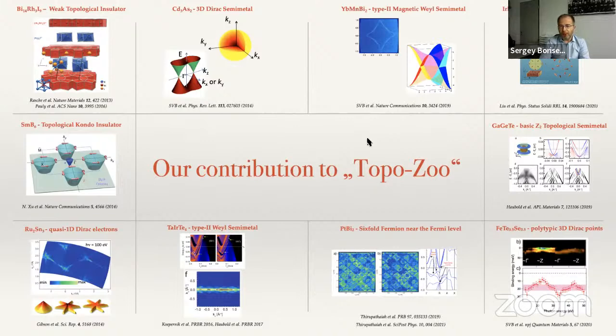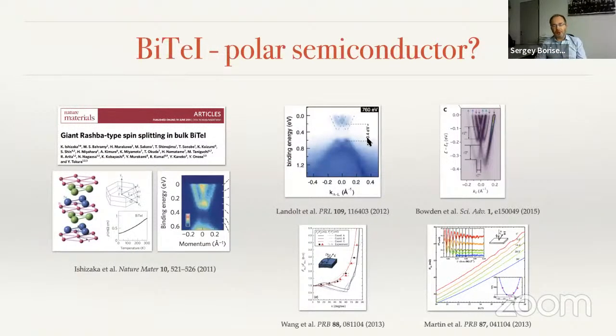So from this point of view, we paid our attention to this material as it was very well known, but so far not topological, in the sense that it has got a huge spin-orbit interaction. And probably the resurrection of interest can be dated to 2011 after this paper, where the spectrum showed that there are states looking Rashba-like, and this was attributed to the bulk bands of BiTeI. The resistivity always shows that it is a metal, right? But the common wisdom was that it is a polar semiconductor. Soon after this paper, there were other ARPES reports saying that actually these are purely surface states.